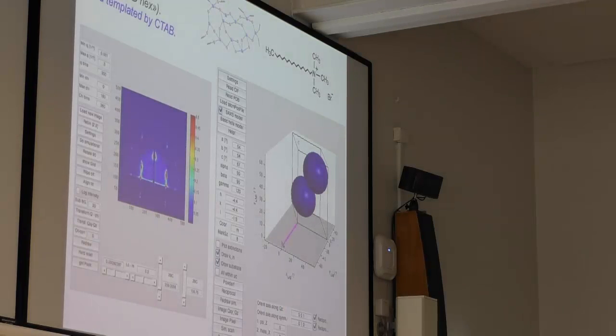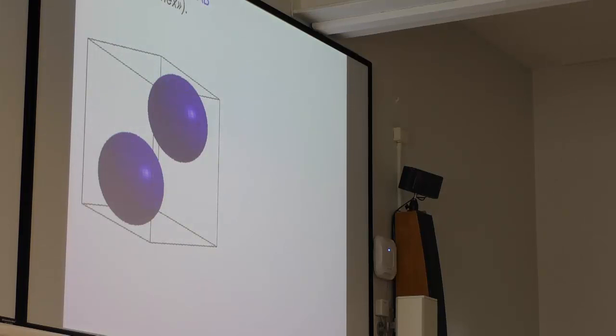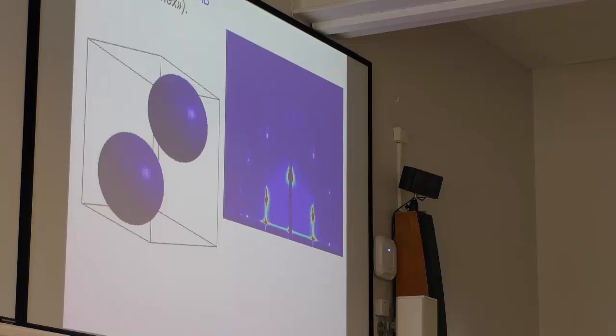So rather than going into the details about that, I will just mention briefly an example with silica that was templated using the organic molecule CTAB. And this forms a so-called 3D hex structure, which, the scattering pattern looks like this. And I'm not expecting you to see anything suspicious here, but there is in fact one thing which is a bit surprising, and that is that if you bother to calculate the structure factors, you will see that there should have been some diffraction peaks here,